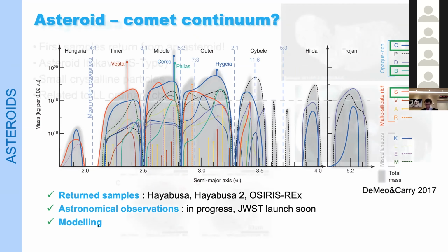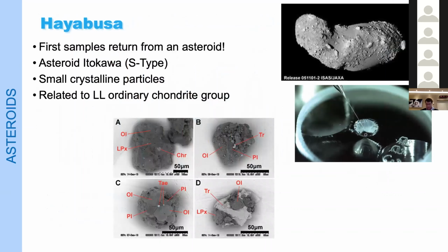So now I'm going to talk a little bit about the different missions that have returned samples. So Hayabusa returned the first samples from an asteroid in 2010. This was an S-type asteroid, Itokawa, here. And the mission actually was not completely successful. They thought maybe they had failed, but very small particles were retrieved from the canisters. You can look at the particles here, which were imaged with a scanning electron microscope. They are coarse grain particles, mostly olivine, pyroxene, silicates and sulfides. And the analysis showed that they're related to a type of ordinary chondrite, which is one of the most abundant types of meteorites in the collections.